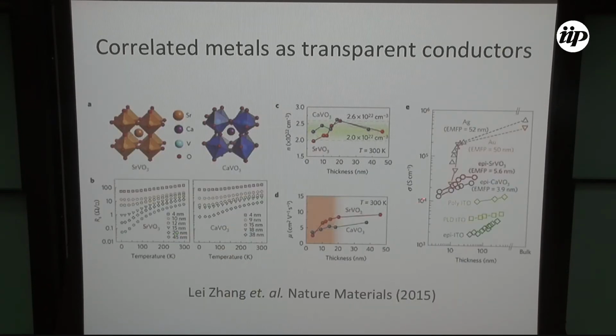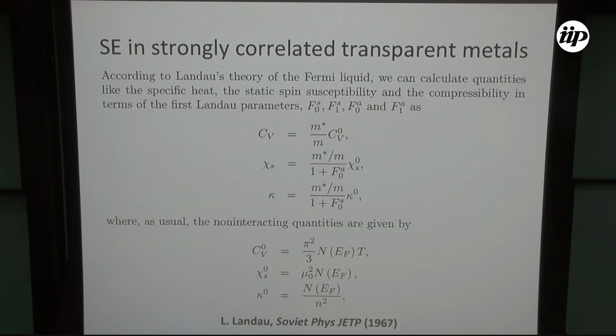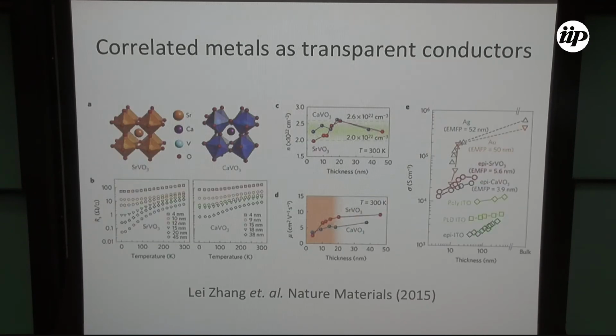And not only that, this is the carrier concentration. It's 10 to the 22, so it's larger than ITO, which is the semiconductor with the highest number of carriers. They have a large conductivity, mobility, and resistance. This is their crystal structure, so they are really well suited for being a transparent metal. This is the next, yes.